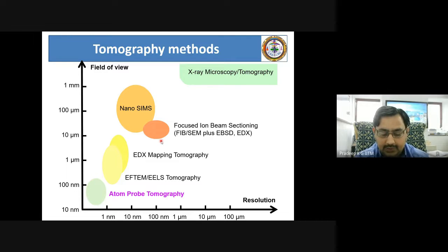That means, depending on the size of your nanoscale feature, we can have something like focused ion beam sectioning, as I showed in the earlier slide, combined with imaging in SEM plus EDS or EBSD. So you will be able to get multiple slices and the projected or diffracted view of the microstructure of those individual slices. If you go down further in resolution, then you reach electron microscopy, where you can do energy dispersive X-ray spectroscopy for chemical mapping in 3 dimensions. Or at best, you can achieve atomic resolution using atom probe tomography, with a reasonable field of view of 100 nanometers to a micron. So this is the largest that you can get today. But the advantage is you are able to see individual atoms clearly visualized in a 3-dimensional space.